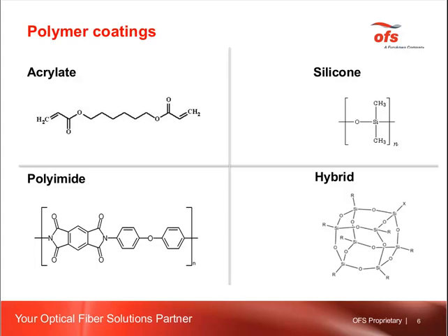Molecular-wise, there are four main chemistries which are successfully used for coating optical fibers. Most common are acrylate coatings. All these formulas, of course, are oversimplified. Less common are silicones and polyimides, and even less common, but more and more popular recently, are so-called hybrid formulations, which are hybrids between organics and inorganics. They have a silica-type backbone, Si-O-Si, from which some organic radicals are evolving. For instance, acrylate groups can be included in these organic radicals.